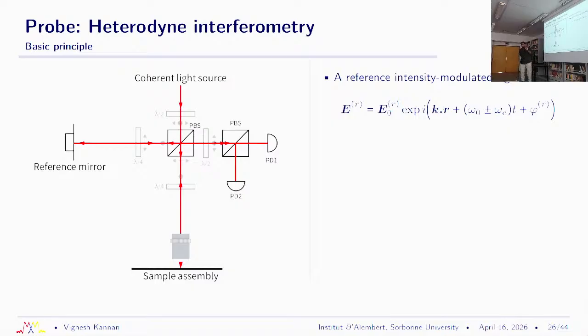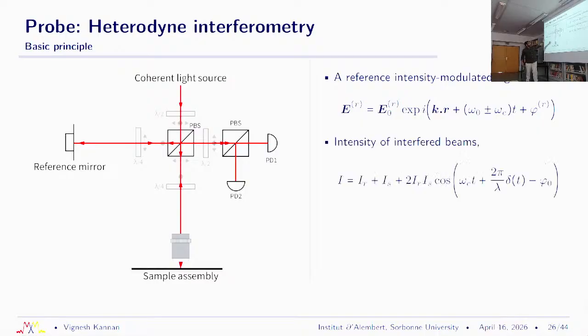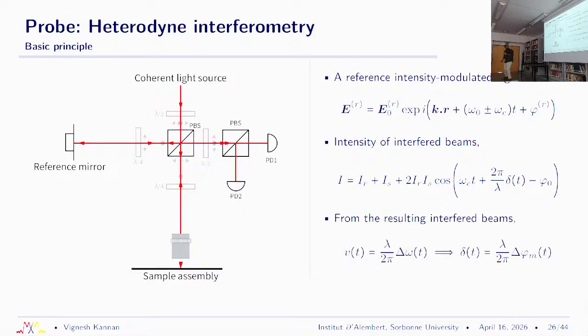But what we ended up doing was building a heterodyne interferometer, where one of your reference legs is now offset by a given frequency. You use an acousto-optic modulator, which I haven't shown you here, I'll show you in a second, that creates an ambient beat frequency. In our case this was 80 megahertz under an ambient condition when there is no wave propagating through the system. And when there is a wave that comes through the system, you actually measure the change in phase of this carrier frequency. So now we are not limited to the hundreds of terahertz frequencies of the optical wave itself, but more what's created by this modulation, right? This way, once we can track the change in frequency or the change in phase, that's directly related to the displacement in our system.